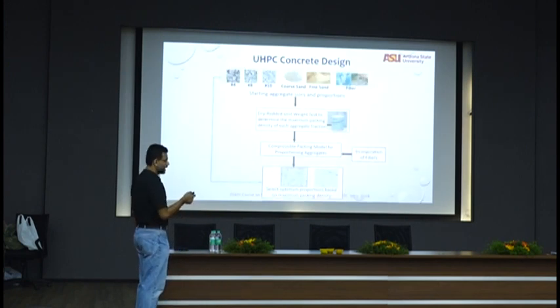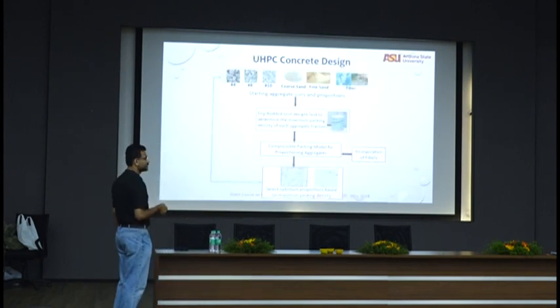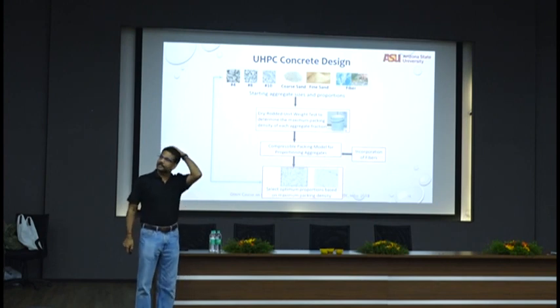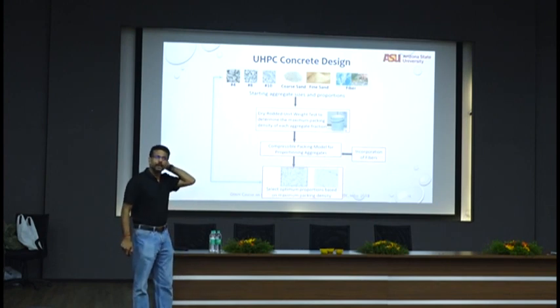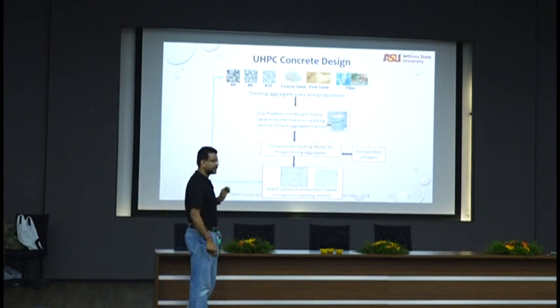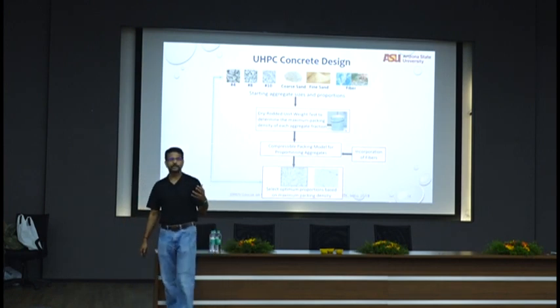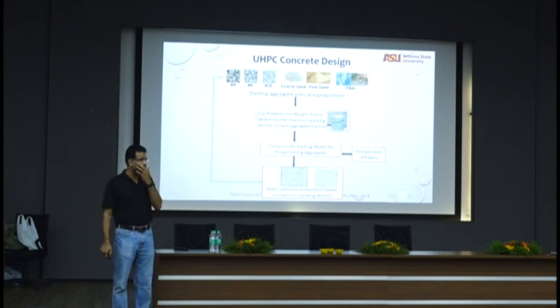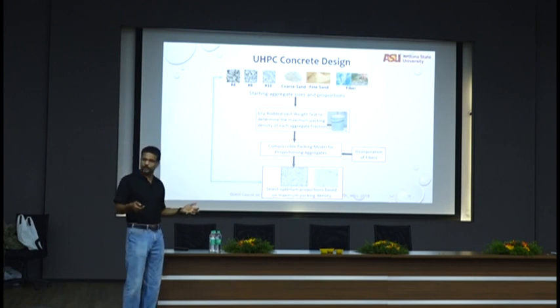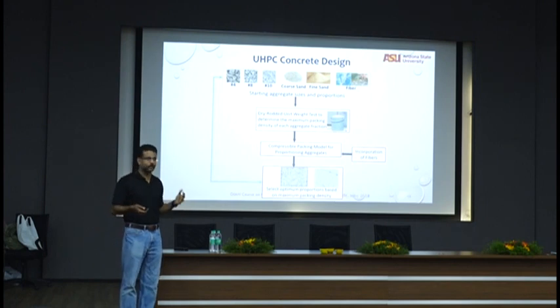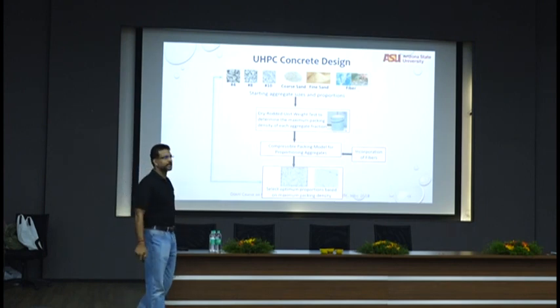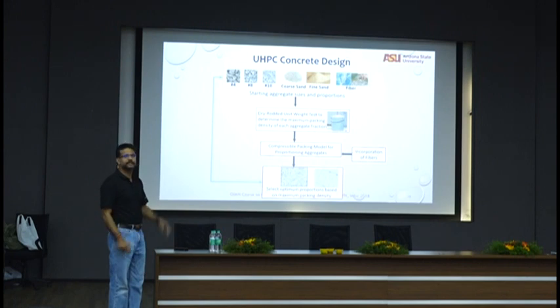Then we started to mix in the aggregates. Normally in UHPC people don't use coarse aggregates; they use only sand. But the problem with using sand is that shrinkage is going to be a problem when you have a higher cement content. If you use coarse aggregate, the structure is going to be more stable, because the aggregates are more stable. So I wanted to use coarse aggregates. I said I have to use coarse aggregates and we'll design it that way.